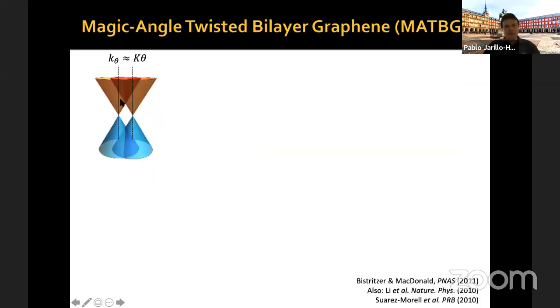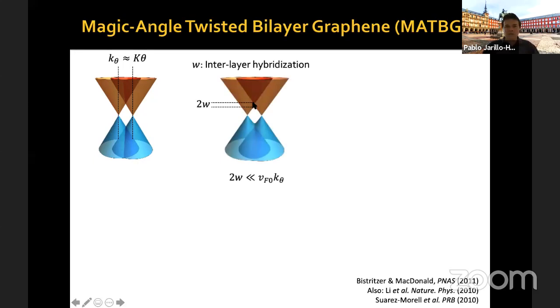This is the situation that would occur if the electrons in one graphene sheet didn't know that the other sheet exists. The two Dirac cones would just interpenetrate each other like this. However, because these two graphene sheets are just 3 angstroms apart, electrons can tunnel between them. This leads to interlayer hybridization, and you get a gap, a band repulsion at this crossing point. You can think of this as bonding and anti-bonding states in a hydrogen molecule: one band gets pushed up, another band gets pushed down.